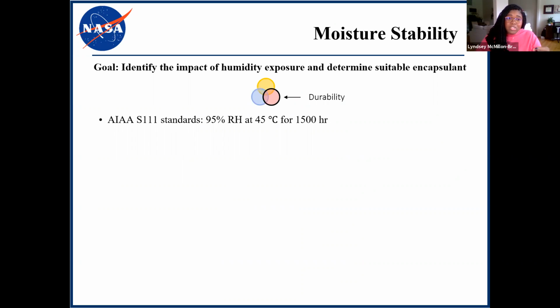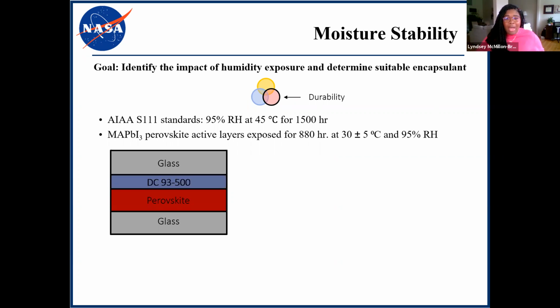And AIAA S111 standards require passing a 95% relative humidity test at 45 degrees C for 1,500 hours. And these standards actually are meant to be representative of the time a solar cell will spend on the ground prior to launch. So we studied a low outgassing, two-part space qualified silicone encapsulant, DC-93-500, and we wanted to see its ability to protect perovskite cells from moisture.